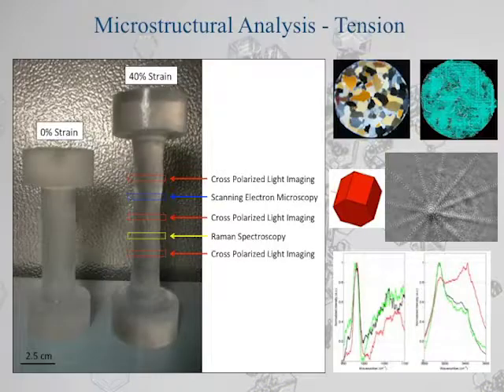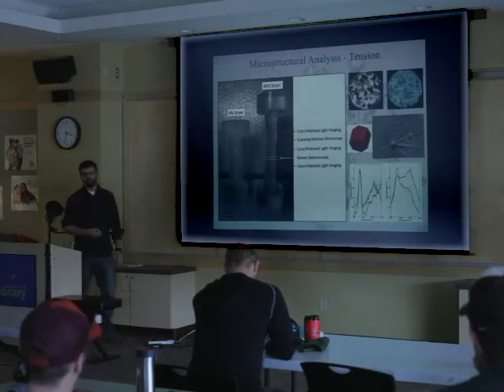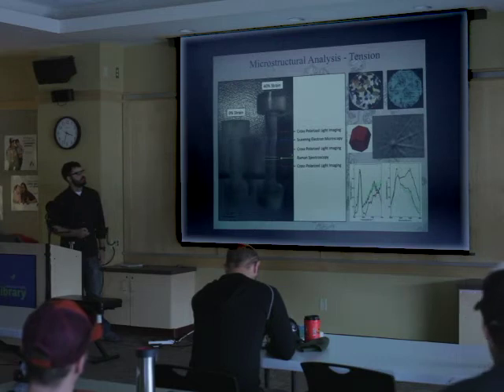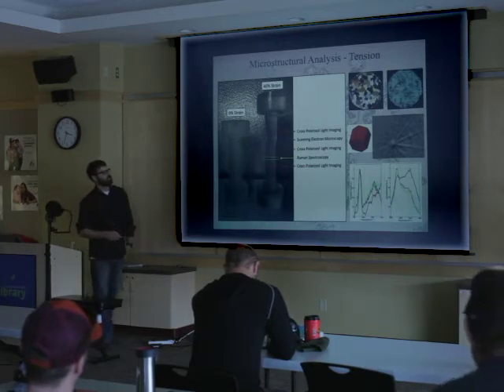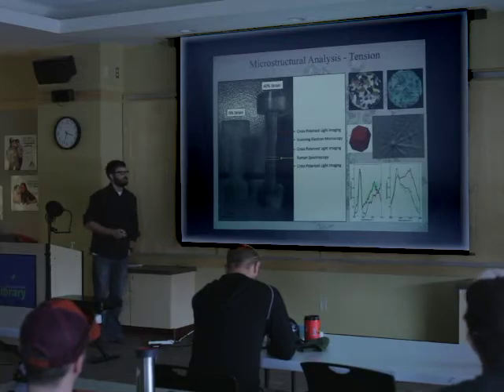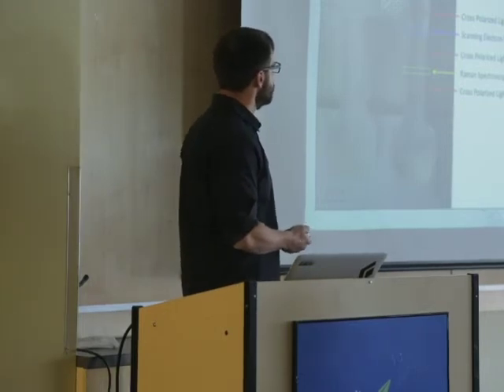Then for the tension-tested specimens, here's what a piece of ice looks like after it's been literally stretched to 40% strain. This probably took somewhere around 6 or 7 weeks to get to that point. We did the same thing: cross-polarized light imaging, SEM, and then also Raman spectroscopy, which I'll talk about a little bit later on, on these samples to try and see what the effects of sulfuric acid was on the microstructural evolution. So, let's jump into the results.